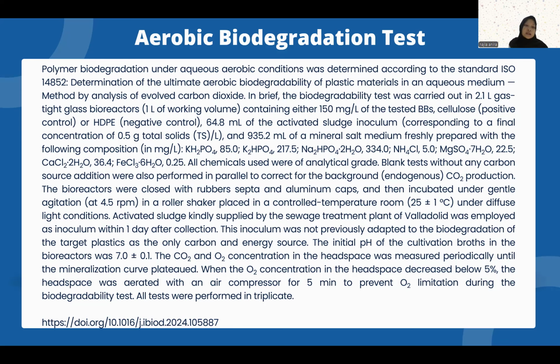Blank tests without any carbon source addition were also performed in parallel to correct for the background endogenous carbon dioxide production. The bioreactors were closed with rubber septa and aluminum caps, and incubated under gentle agitation at 4.5 rpm in a roller shaker placed in a controlled temperature room, 25 plus minus 1 degrees Celsius, under diffuse light conditions. Activated sludge kindly supplied by the sewage treatment plant of Valladolid was employed as inoculum within 1 day after collection. This inoculum was not previously adapted to the biodegradation of the target plastic as the only carbon and energy source.